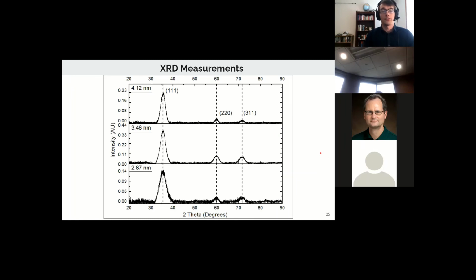This data displays the XRD data taken for Scherrer-derived sizes of 4.12 nanometers, 3.46 nanometers, and 2.87 nanometer particles, all showing strong line broadening. The 111 peak is the largest, which agrees with the TEM measurements, and it also confirms the TEM insights as being the dominant lattice spacing. The 220 and the 311 peaks were comparatively weaker, but all three lined up with the expected diffraction peaks for the cubic or beta polymorph of silicon carbide.